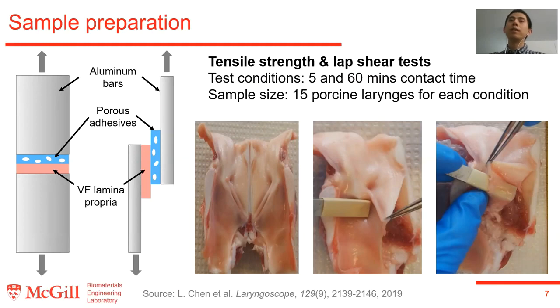We use the tension test and the lap shear test to measure the tensile and shear strength of our adhesives to lamina propria. Fresh porcine larynges were obtained from a local slaughterhouse. For each test, we first mounted the lamina propria to a aluminum bar and the porous adhesive to another bar using the superglue. After that, we brought the tissues and adhesives into contact for 5 and 60 minutes before the testing. We repeated the test 5 times for each condition to get the mean values.